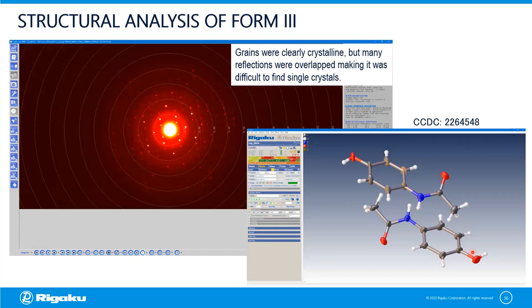And this has been deposited in the CSD. You can see that the thermal ellipsoids here are much, much better. It's two molecules in the asymmetric unit. You really can't see this very clearly, but the R1 is really quite good for an electron diffraction experiment.